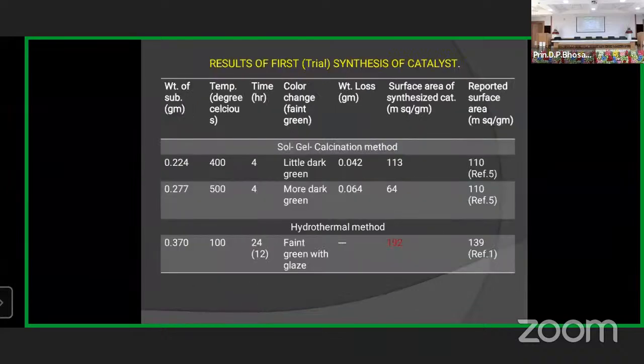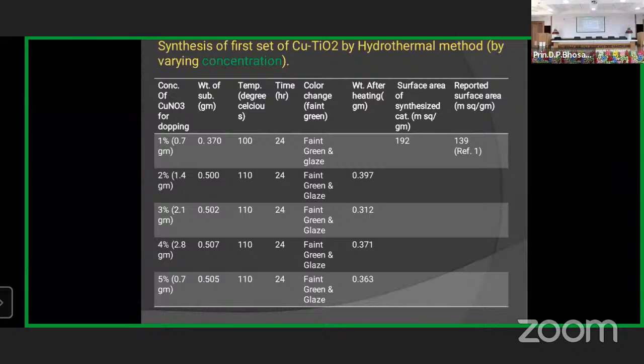These are the first results for the IR, which I have made on a trial basis only. Very soon, after doing the proper synthesis, we will have better ones. Next, these are the results of the preparation of the copper doped TiO2 catalyst by the hydrothermal method. Here we prepared 1%, 2%, 3%, 4%, and 5% copper doped TiO2, where the precursor is titanium isopropoxide, and the doping is done with copper nitrate.